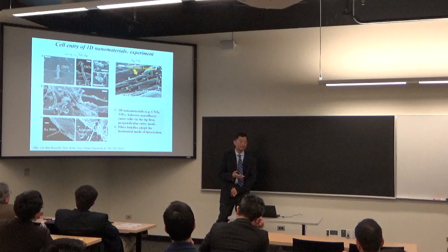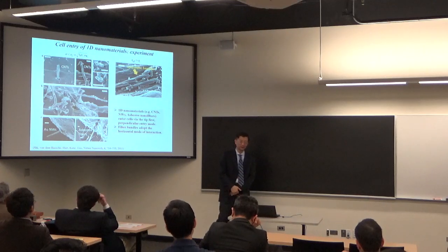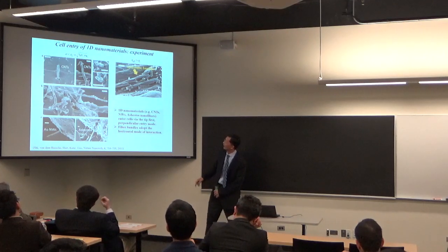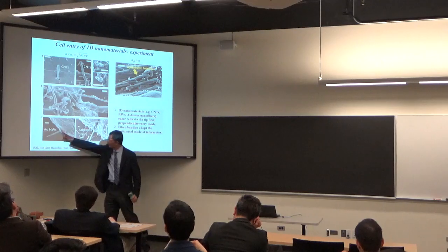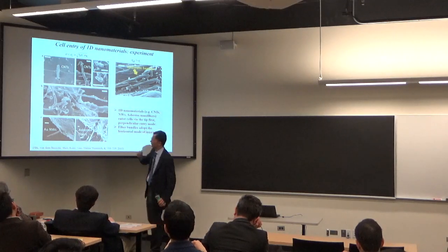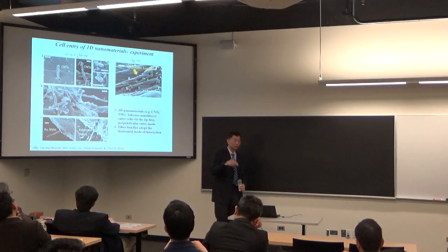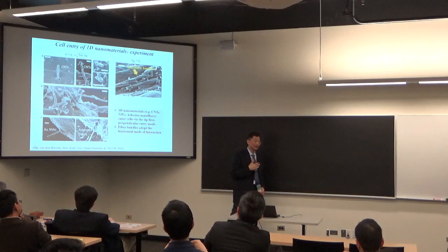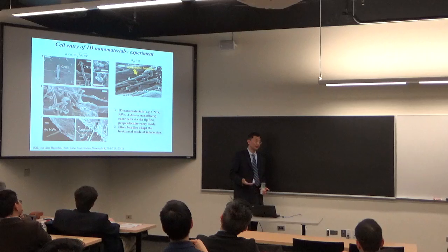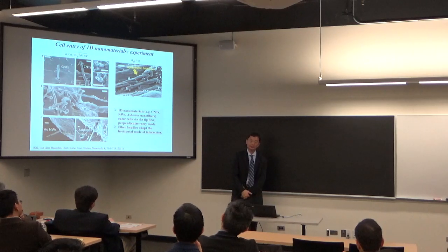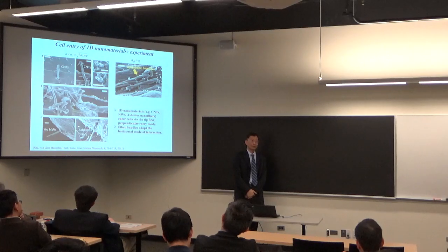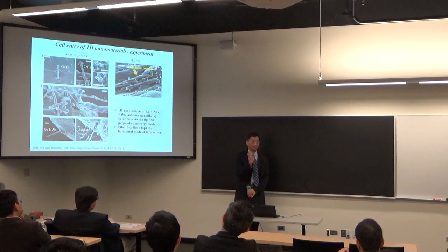In the bending dominant regime, within the subcritical regime, we find in each case this material goes into the cell in a perpendicular way. This is like a bullet shooting into armor, right? But yet there are no dynamics. This is a spontaneous biophysical process. The bending deformation of the membrane automatically orients the fiber into a 90-degree orientation.